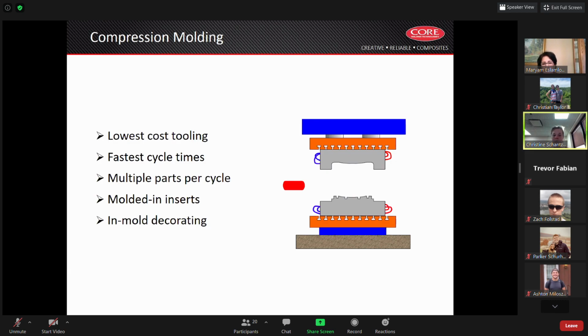The one problem that you do have is, as soon as you take that preform that's at molding temperature and you set it in a mold cavity, that material does start to cool immediately. Actually, as soon as it comes out of the accumulator, it starts to cool on the surface. So generally, compression molding is used for less visual parts that don't have as tight visual criteria for our customers, because you will see what we call a footprint. You will see that cold material that's either come in contact with the mold surface or even the conveyor that the preform comes out on. You will tend to see that on the part surface in the compression molding part.